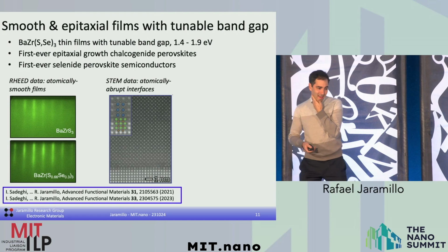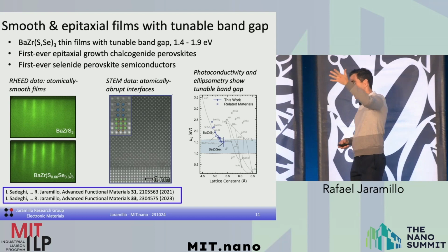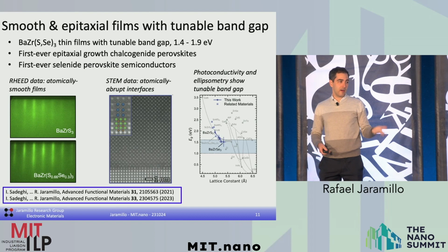And this is now our addition to the Cho plot. We've done it with a little bit more sobriety. So this is actually based on data. We're putting our own alloys on this Cho plot and showing how we're able to realize the theoretical predictions of the tunable band gap, getting into that range optimal for single junction solar cells.